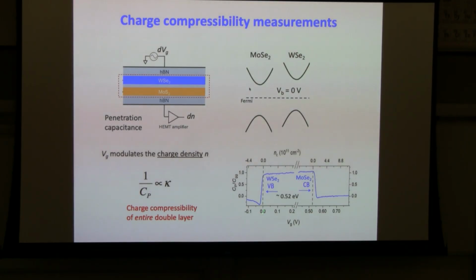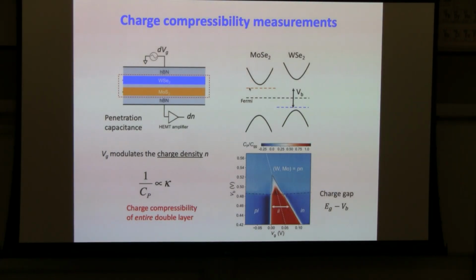By directly reading the energy difference or the voltage difference between this valence band edge and the conduction band edge, that will give us the energy gap of the system, which is the energy gap between the conduction band minimum and the valence band maximum. And in this particular case, it's about 0.5 eV. So half a volt, the energy difference from here to here. And that's for zero bias.